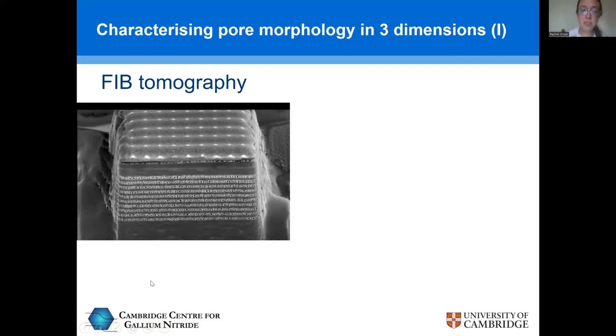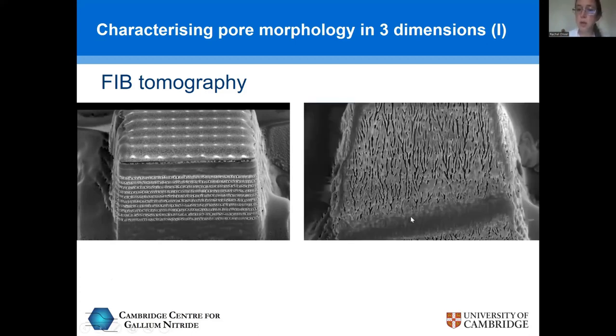What we can do with the data set that we get from that experiment is essentially reconstruct the full three-dimensional structure of the porous distributed Bragg reflector. What I'm showing here is just one layer now looked at from the top rather than in cross-section from the side. And this isn't a real image. This is an image which is made up from all the sections, and then we've digitally cut it out to look at a single layer of the distributed Bragg reflector.